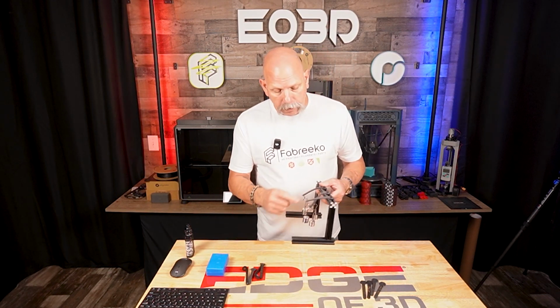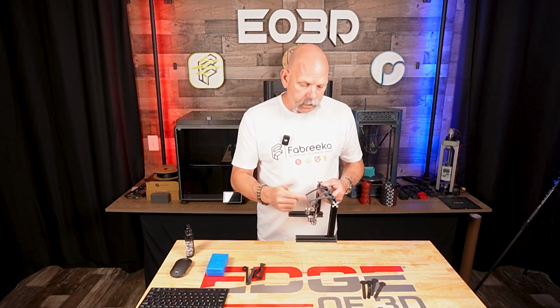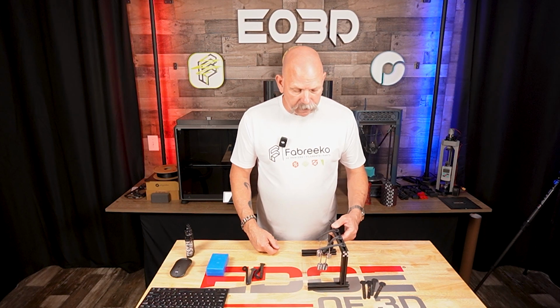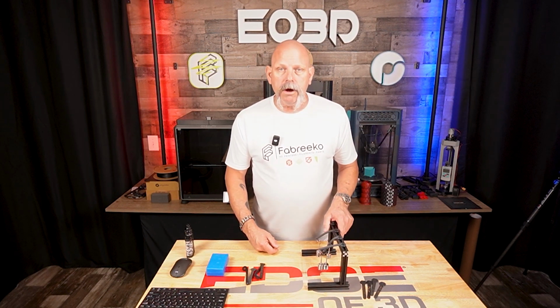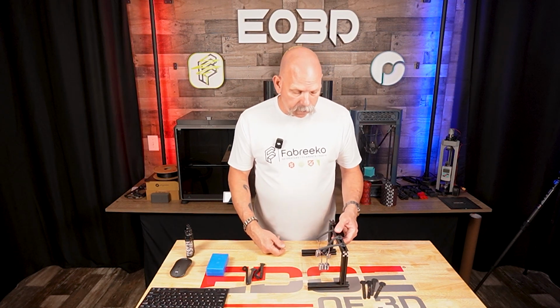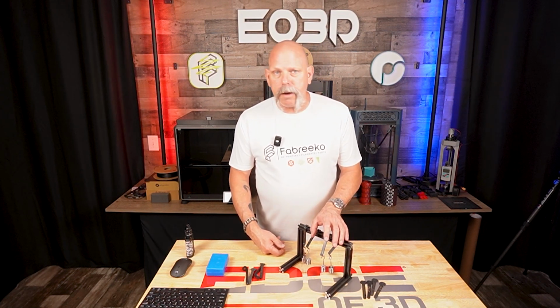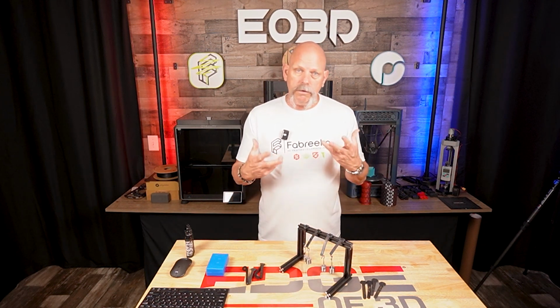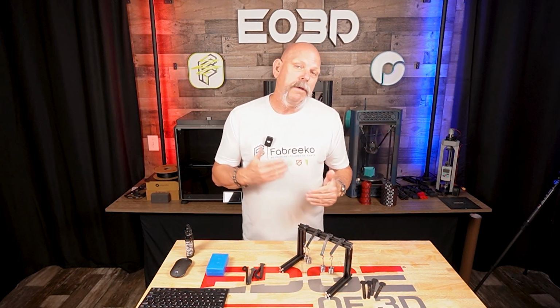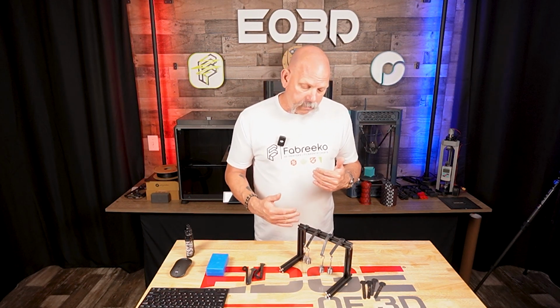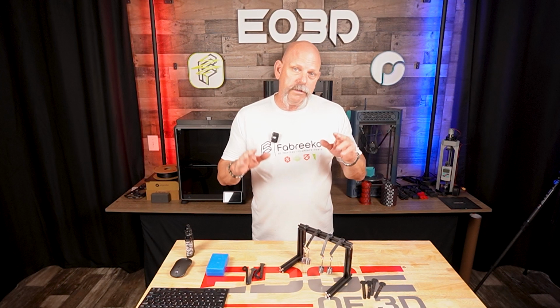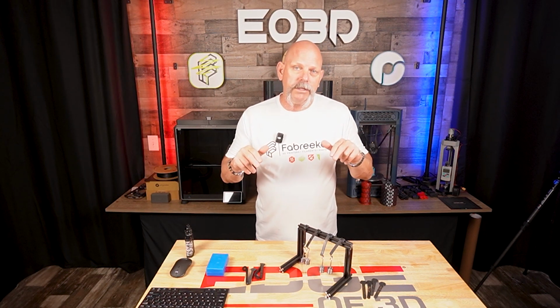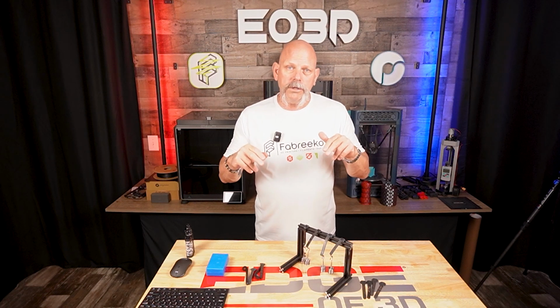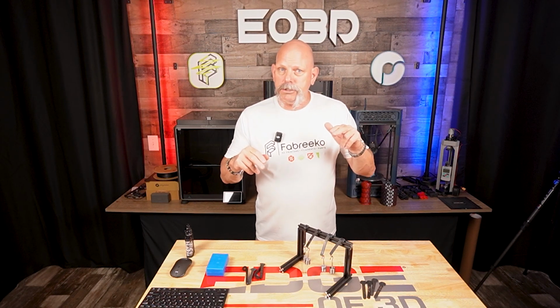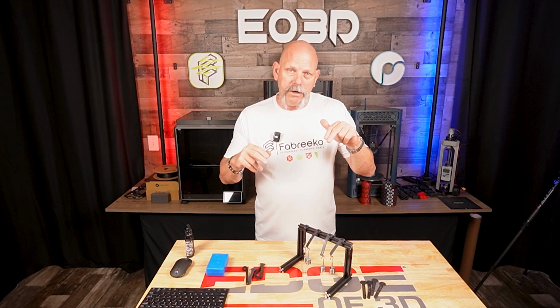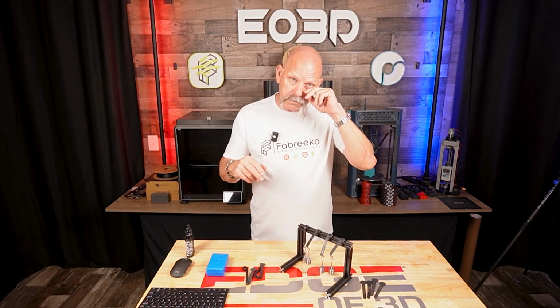You know, the PPS carbon fiber, it started to really give out fairly early on. The PET carbon fiber that wasn't annealed, it just gave out altogether. But the PET carbon fiber annealed and the PPS carbon fiber annealed, you know, they held on pretty good up into the low hundreds. And the PET carbon fiber, they started to drop at about the same rate for 20 degrees or so. And then the PPS just kind of held on, giving up just a little bit at each step while the PET kept going down more.